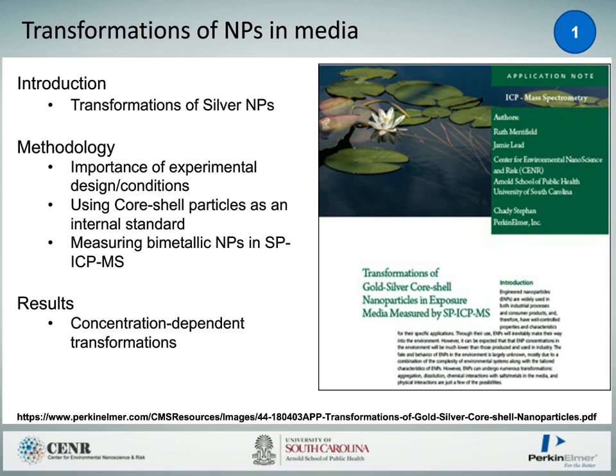The first application I'd like to speak about is the transformations of nanoparticles in media. I'm going to go through a quick introduction on transformations of silver nanoparticles, some methodology, the importance of experimental design, in this case using a core-shell particle so that we already have an internal standard in our system, and measuring bimetallic nanoparticles with single particle ICP-MS. I'm going to speak about one result that we got today, which was looking at the concentration-dependent transformation of silver nanoparticles in moderately hard water. However, we have done a lot more of this study, which you can find in an application note already on PerkinElmer's website.